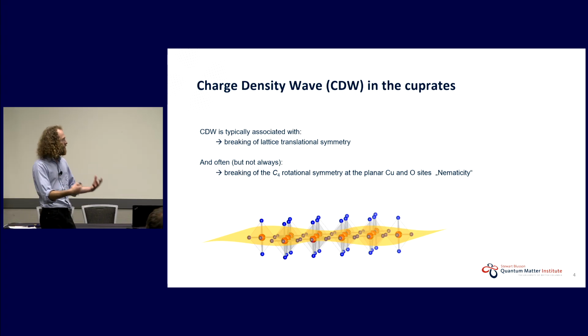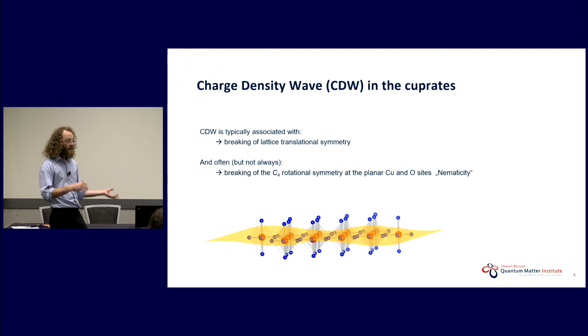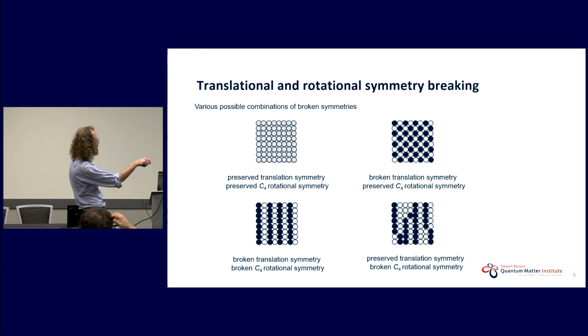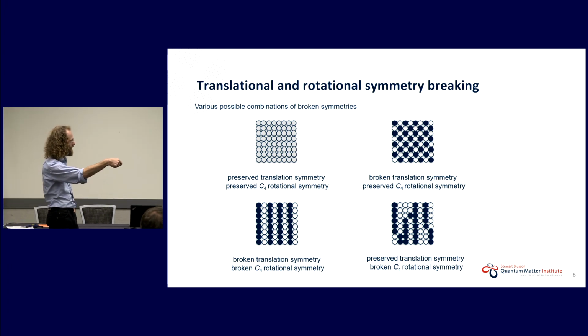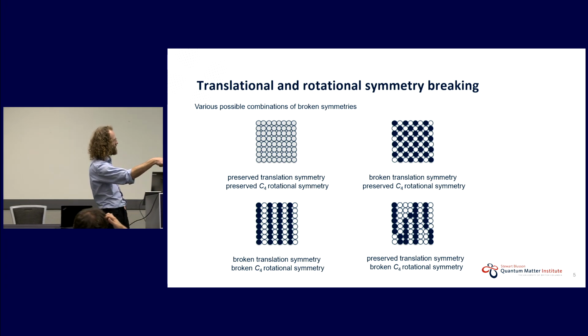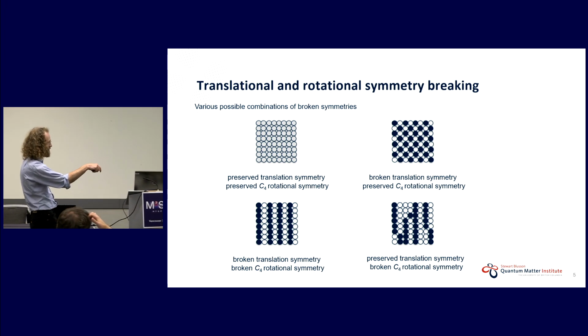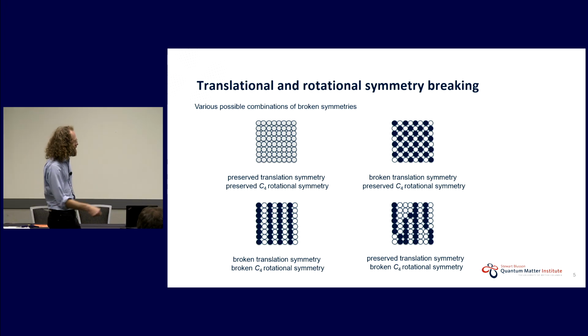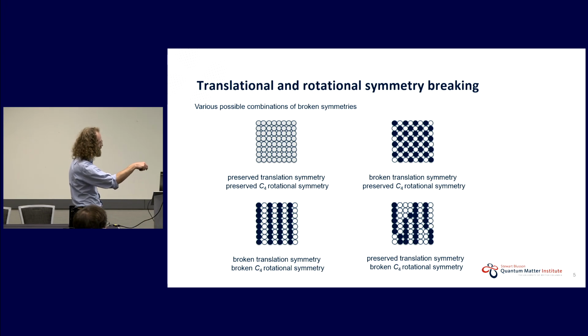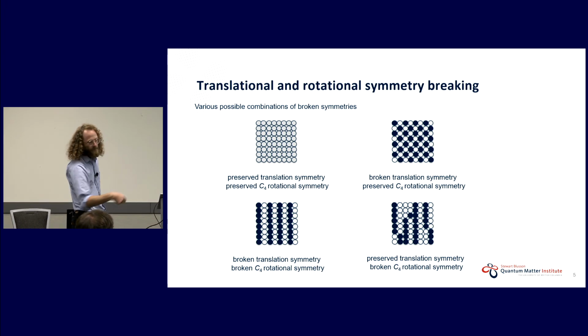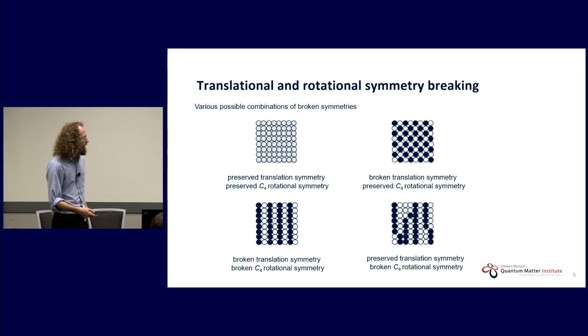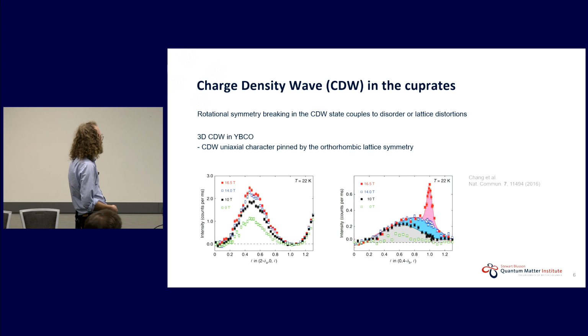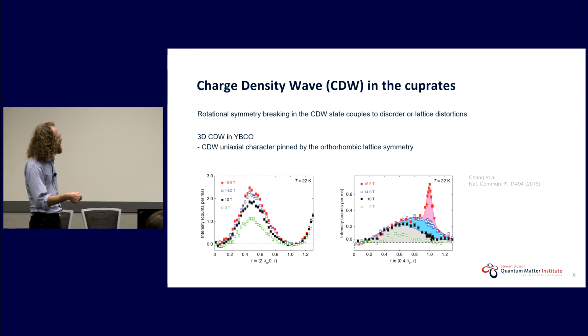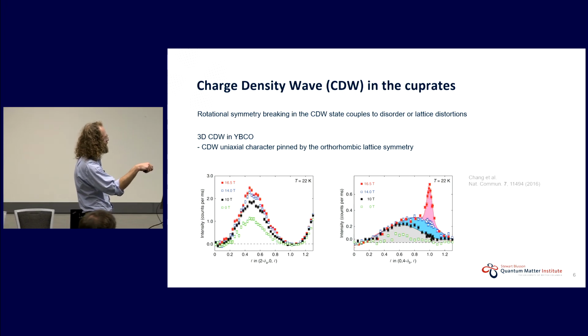So nematicity is often more rigorously thought of as the rotational symmetry breaking without the translational symmetry breaking. But here I want to focus on these two symmetry breakings and how they can happen together or independently of one another. So just to give you a picture of the type of thing I'm talking about, you can have the symmetry of a square planar lattice. You can break translational symmetry in some sort of charge order without breaking rotational symmetry. You can break both rotational and translational symmetry in a stripe-ordered state. And if you introduce enough dislocations and phase slips in this stripe-ordered state, you can achieve a state which has broken rotational symmetry without explicitly breaking the translational symmetry in a long-range way.